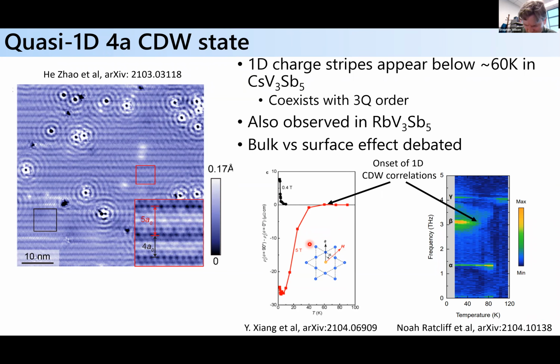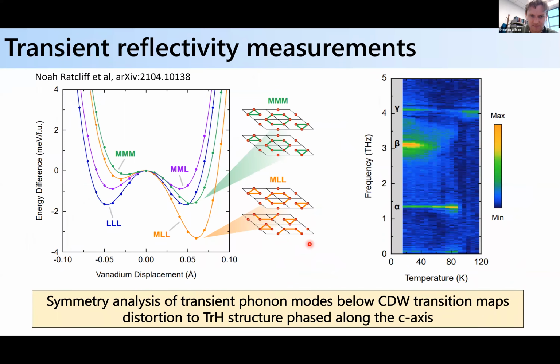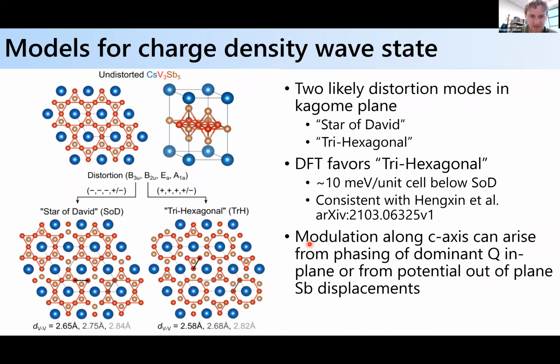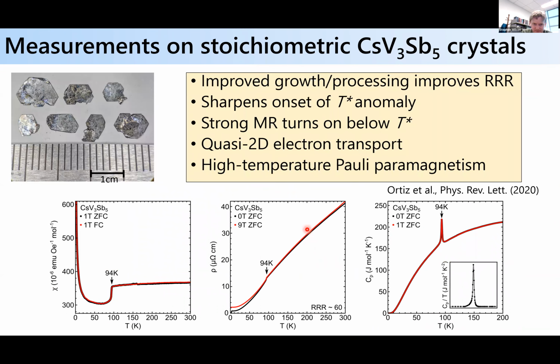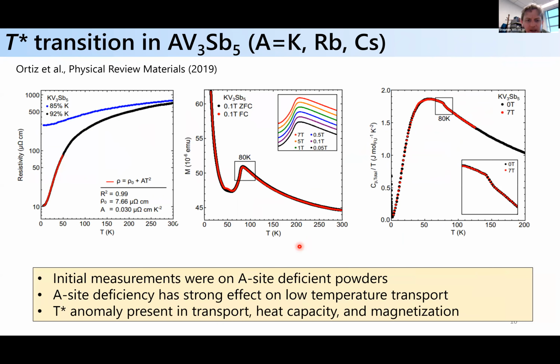In terms of transport anisotropy as a function of temperature, the data we have, let me see. I didn't see a major difference. Let me see if I can pull it up here. Oh, I don't have it in this talk. I don't have the slide, but basically, if we check just the conventional electrical resistivity as a function of temperature along the C-axis, and then overplot that with the resistance in the AB plane, then they kind of map. One is about 300 to 600 times larger than the other, but the ratio doesn't really change as a function of temperature, as far as we can tell.